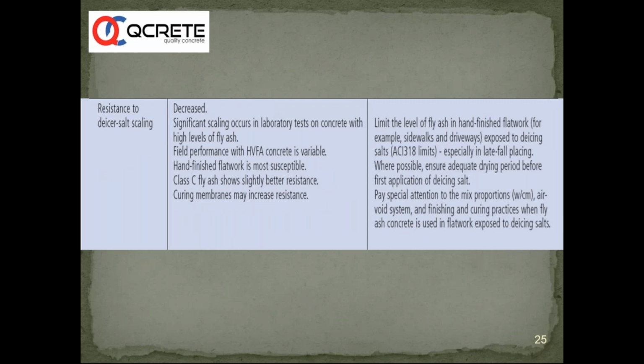So resistance to salt scaling is decreased. It can be countered. We need to reduce the water cement ratio, and we need to design the concrete properly, and the concrete has to be finished properly.